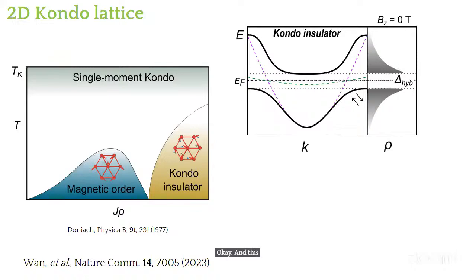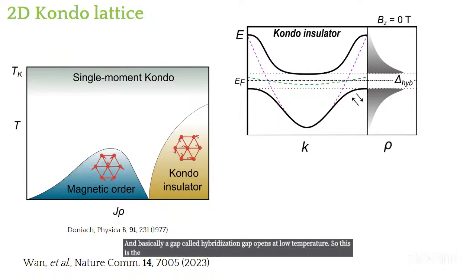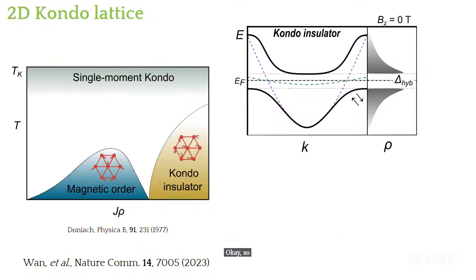And this can be studied through the density of states, which is exactly what we are good at. In the Kondo insulator solution, in principle, you expect two bands to play the whole game here. This purple band represents the conduction electrons, and the green band, which is more localized, represents the magnetic moments. Okay, so the interaction between these two bands leads to the formation of two bands around the Fermi level, and basically a gap called the hybridization gap opens at low temperature. So this is the signature of coherence, okay?